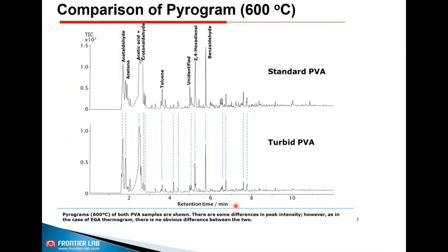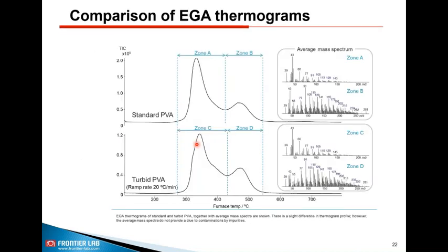As you know, generally, if you want to find a quick and dirty answer, we always try to do a flash pyrolysis. But what we can see here is that the flash pyrolysis data is not giving the information you are interested in, because by looking at this data, we feel there is no difference between these two, but there is a difference in terms of physical appearance and quality. So that means we have to go for a systematic approach that starts with the EGA. Here we have started with the EGA, the evolved gas analysis, for the standard and the turbid product.